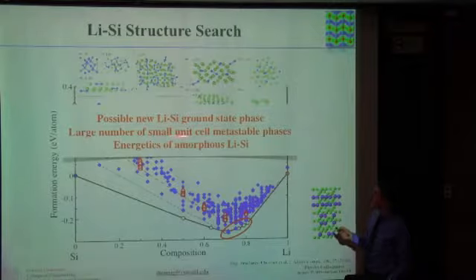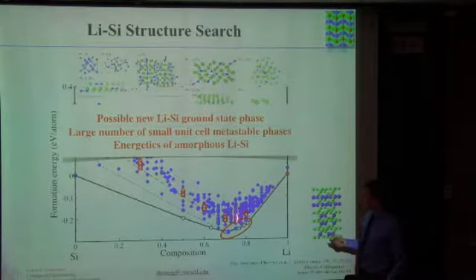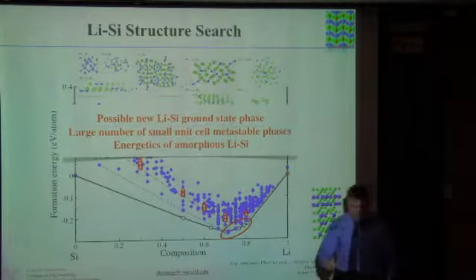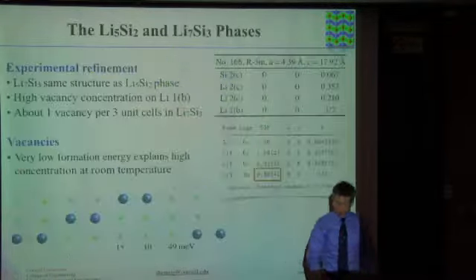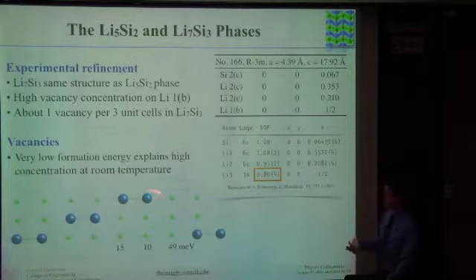We found a large number of small unit cell structures. Almost all of them are metastable. A couple of them are close to the convex hull. And we have the energies of the amorphous lithium silicon. We're going to use that information to figure out what the voltages of the lithium silicon electrode are. First, let's look at that new structure. Here's an illustration of that.